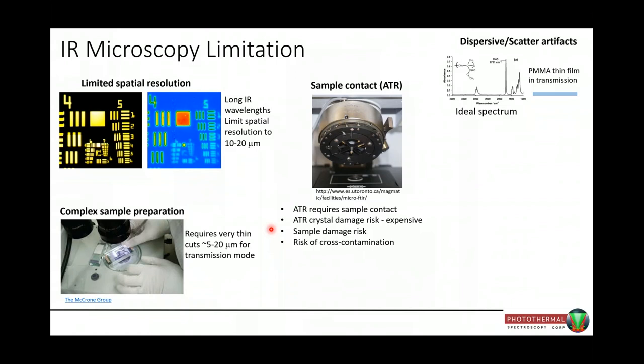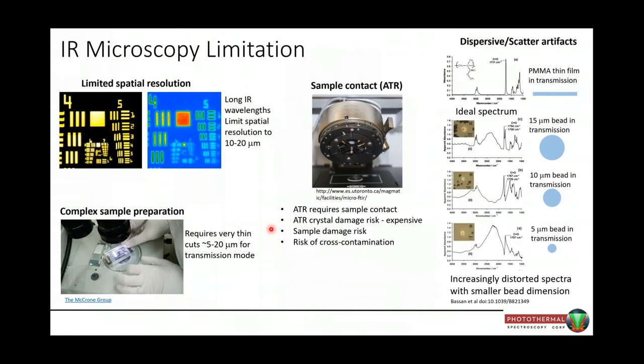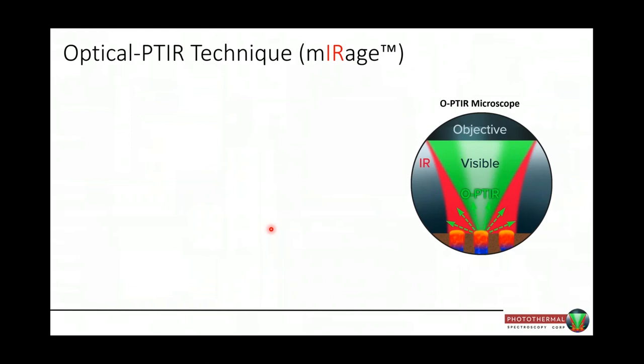If you measure the transmission spectrum of a 15 micron bead, a 10 micron bead, and a 5 micron bead, you can see the spectra start to distort dramatically as you change the dimensions of the sample. With the new optical photothermal mirage technique, you can get around all four of those problems with infrared spectroscopy.